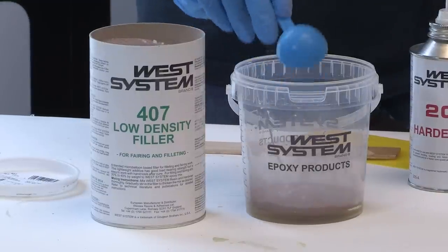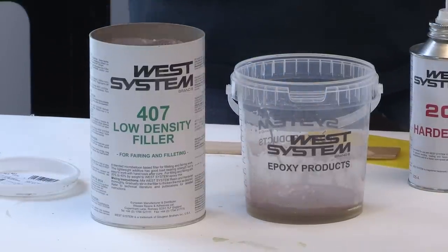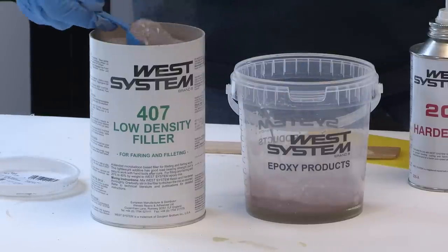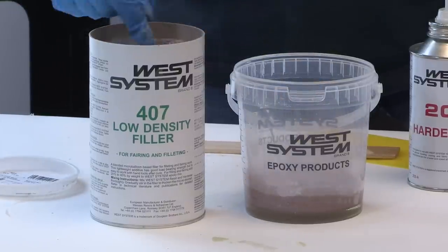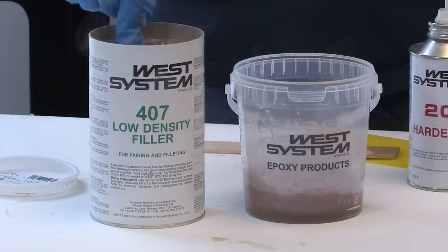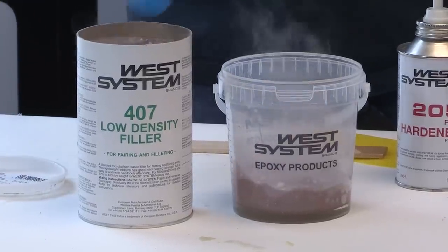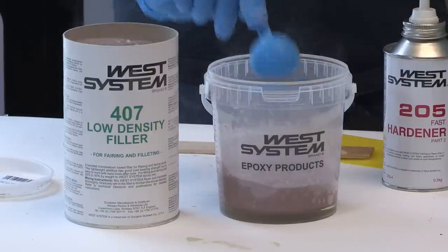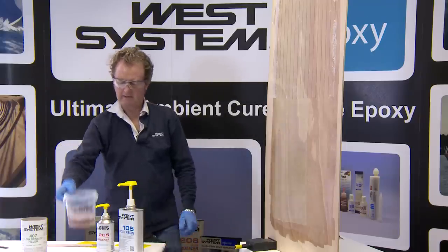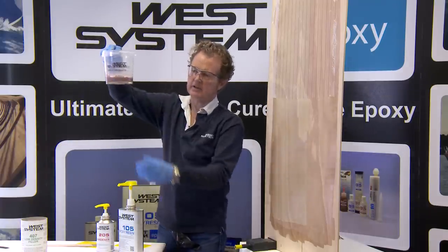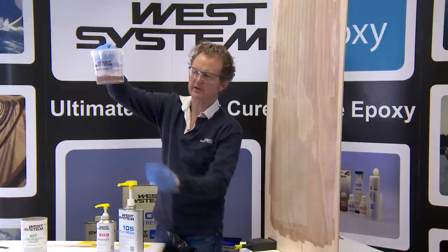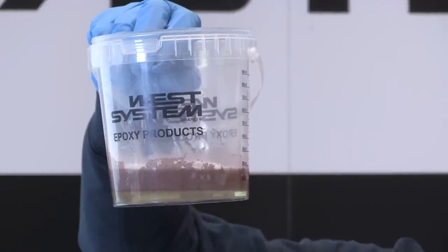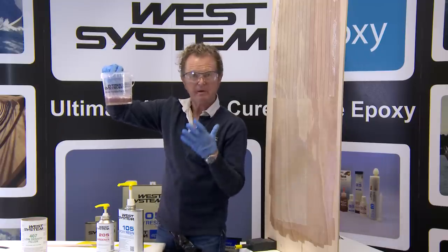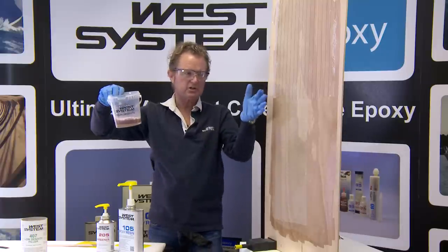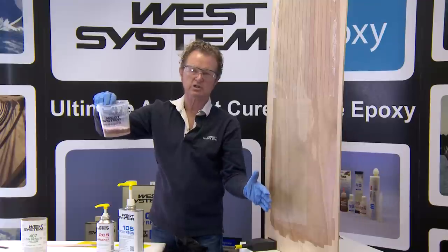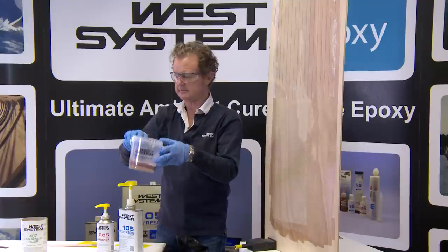Now for each pump of resin, we need approximately 2 scoops of the low density filler. Now this appears to be quite a lot of filler. So for this, I'll need 6 scoops. And if you look at that, this is around about twice the volume of filler to the mixed epoxy. This should give me close to a peanut butter consistency, which is the kind of consistency that I want to stay on this vertical surface and be very easy to sand.